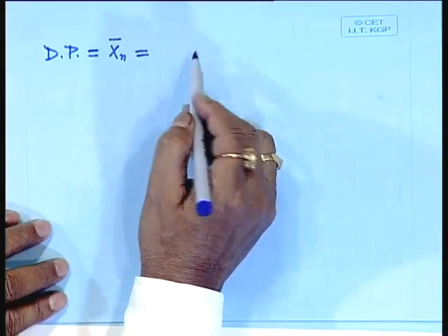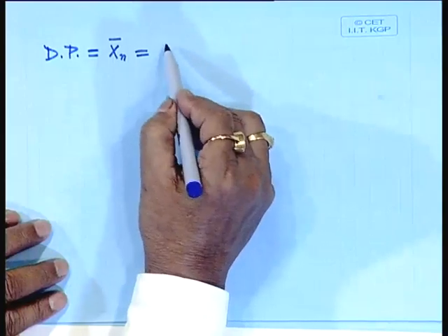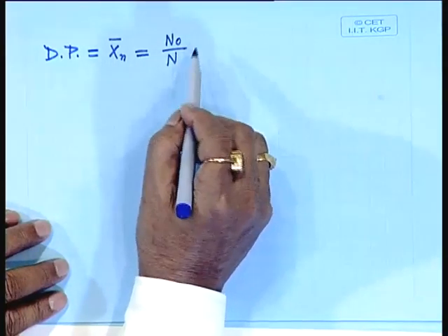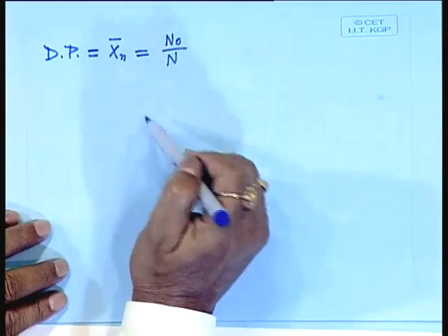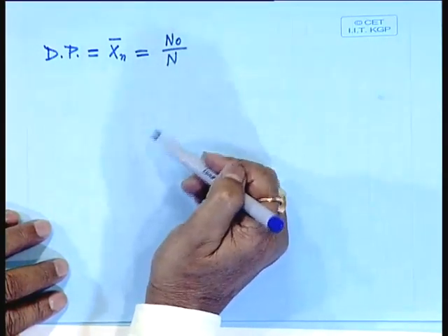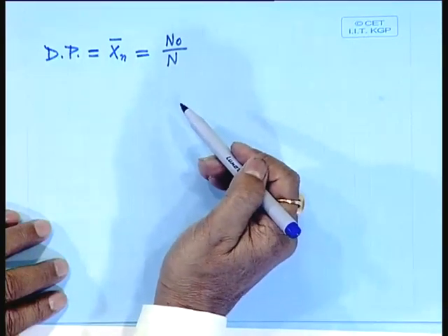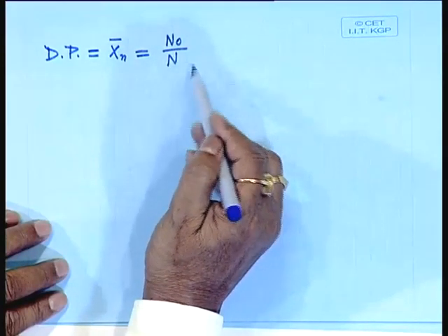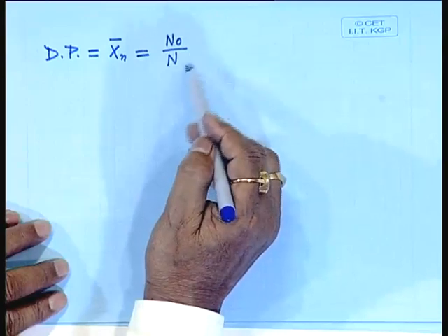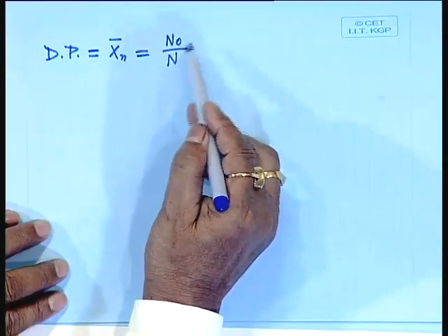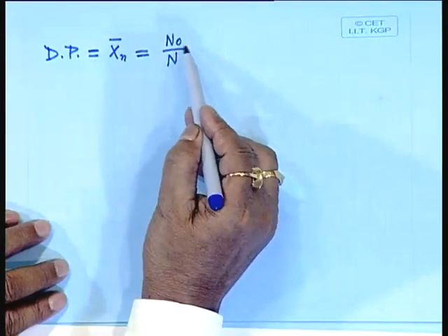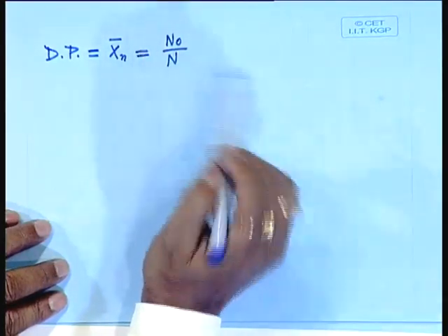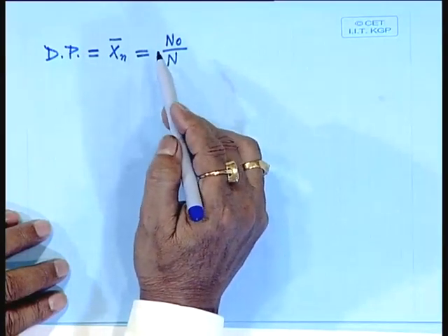All right, we will discuss later in detail. So, the number average degree of polymerization, designated by xn bar, is equal to n0 by n, the number of molecules initially present divided by the number of molecules present at any time during the growth of polymer molecules during polymerization. Is it clear? Do not forget this: xn bar is equal to n0 by n. And if you start with bifunctional molecules, then the total number of functional groups would be twice n0 by twice n, basically the same xn bar.